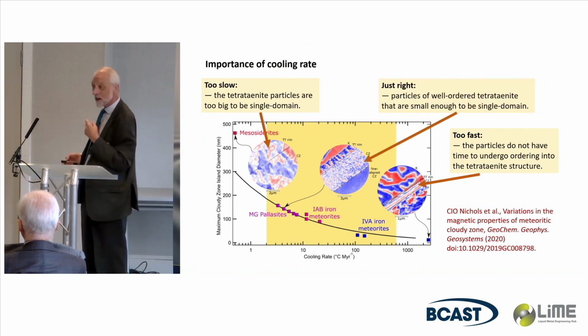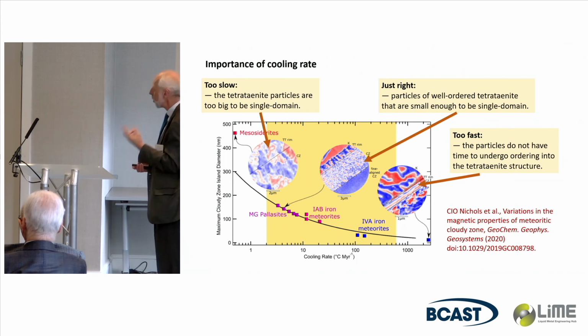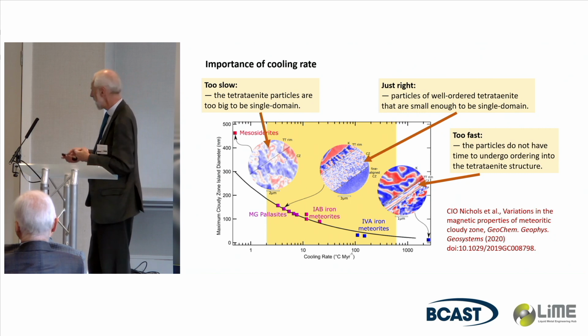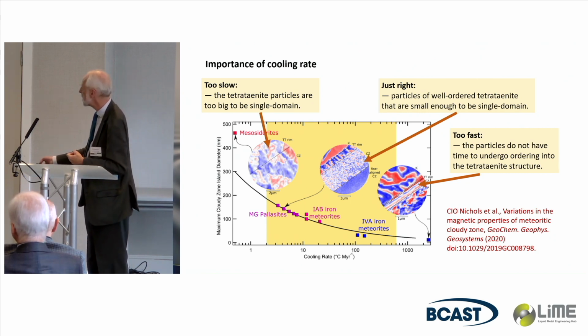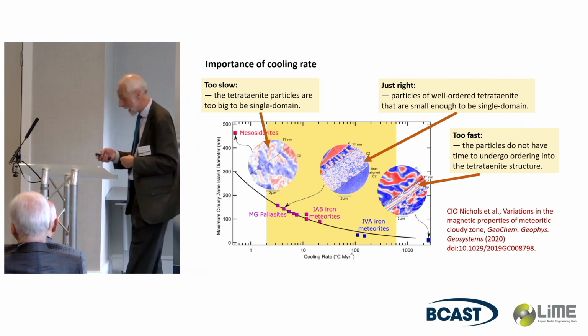But if you're just in the right zone, you get small enough particles to be single domain that are well enough ordered to give you the magnetic properties. And the region over which that occurs is the shaded bit in the middle, which is quite broad, actually.